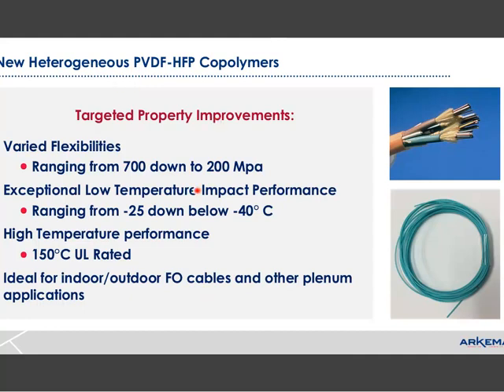But some of these new products that are available provide very wide ranges in flexibility down to 200 megapascals. And most importantly, they offer very good low temperature impact performance. Our target when we started developing these products was to get down below -10 degrees. There are several products out there that are below -25, and there are now some that are well below -40 degrees C for very low temperature applications. All of these products are 150 degrees C rated, good for indoor-outdoor fiber optic, and also for outdoor applications requiring cold temperature performance.